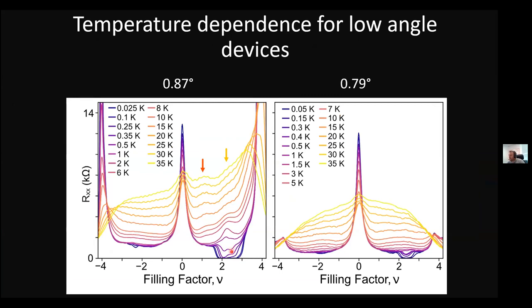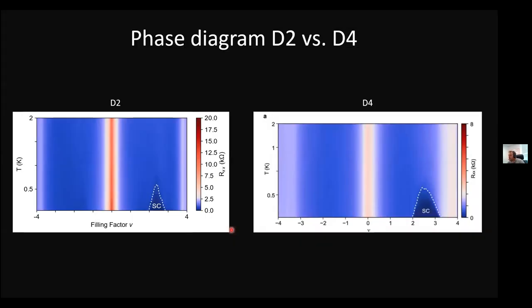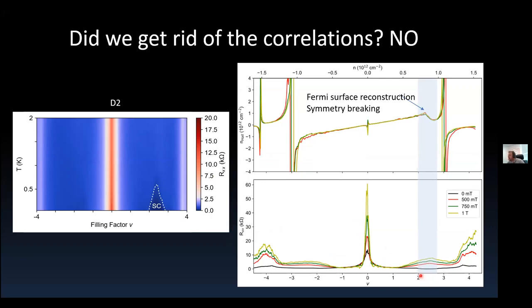And this is now a bit of a detailed question, and maybe also present here. I shaded this region where we see superconductivity. There's definitely Fermi surface reconstruction somewhere in the middle. But if you sit on this point, you are just before the Fermi surface reconstruction, and it seems that there is some superconductivity. So these samples all have metal gates or graphite gates? These are all with the metal gates.